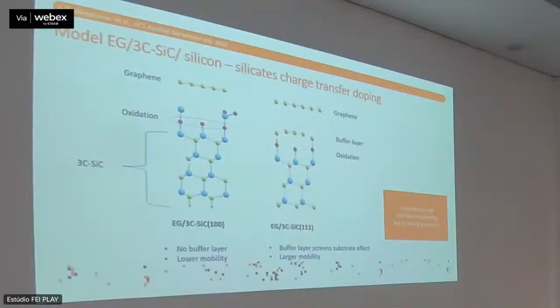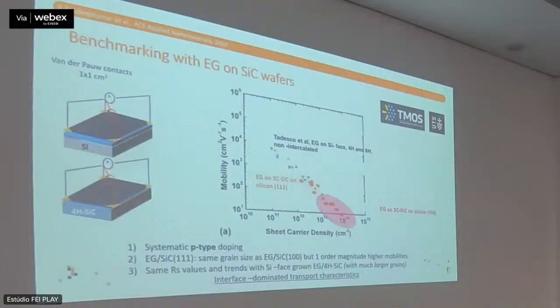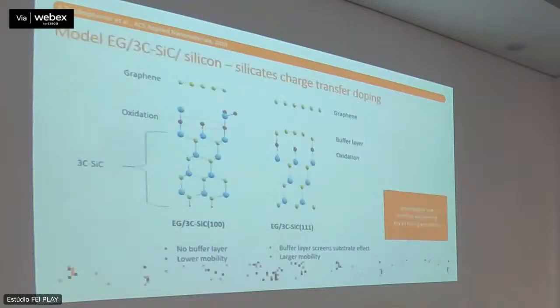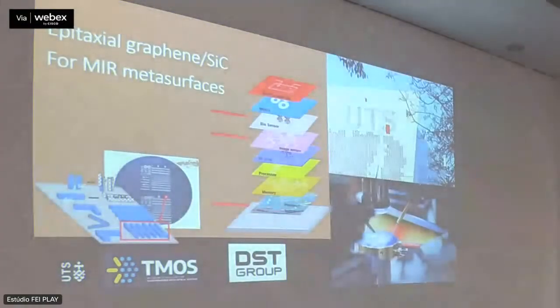We do have also a buffer layer, like the case of the graphene on single crystal wafers, which is a carbon layer which is not acting as graphene because it has every third atom bonded to the silicon carbon underneath. But what effectively this does is that it shields slightly the charge transfer from the oxidation of the silicon carbide. And it's exactly what we see. So 100 with no shielding have the highest amount of charge transfer, so really extreme, you get the density down here, while the 111s are at least partially shielded by the presence of this buffer. So that's exactly what is happening. So this is the difference with the conventional sublimation on single wafers. Right.